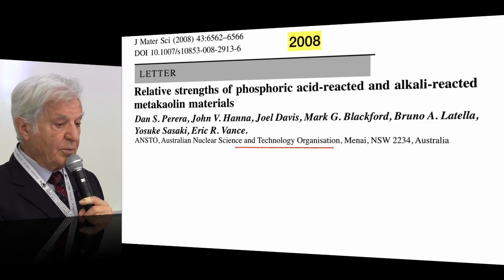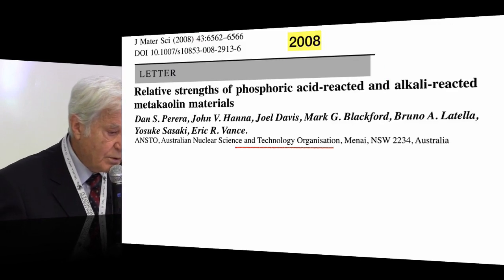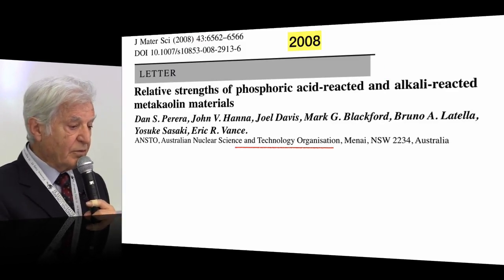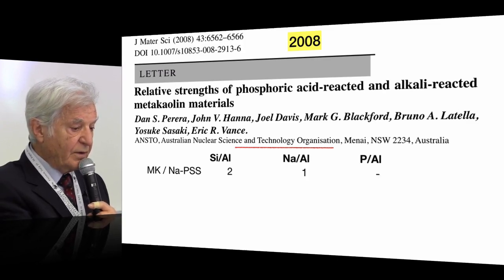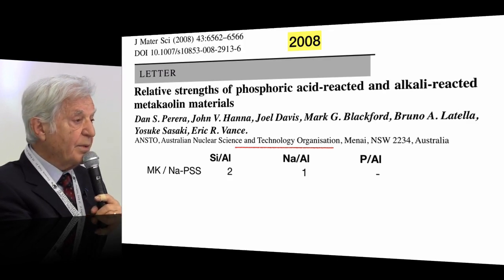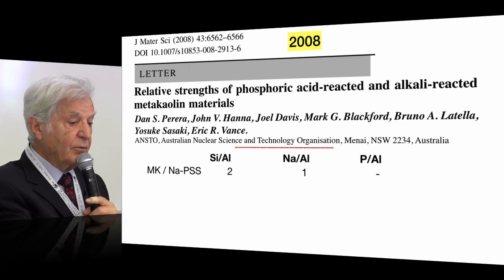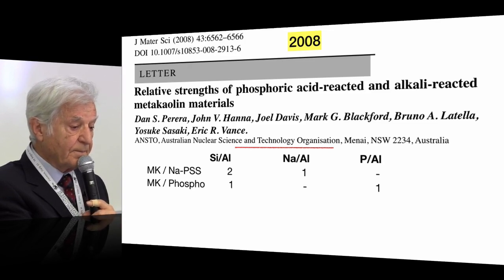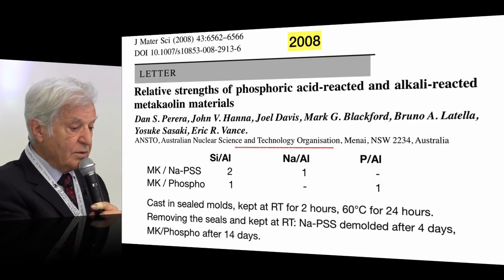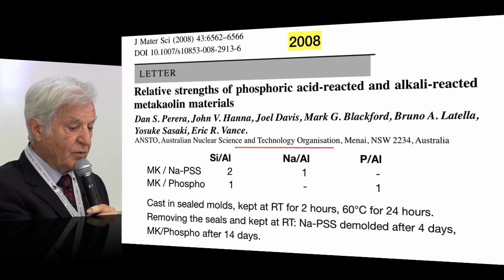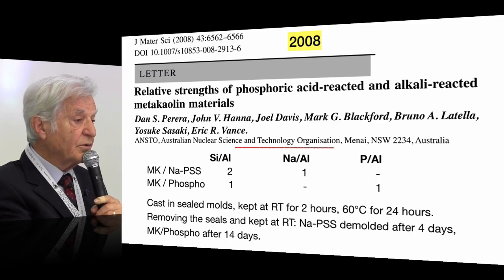So we have a special talk just after this session on phosphate-based geopolymer. The first important paper on that topic, which I consider the first important, was the one published by our friends Perera and his team from ANSTO in Sydney, Australia, where we have Si/Al ratio, Na/Al ratio, phosphate/Al. They compared the metakaolin alkali reaction with the phosphoric acid metakaolin reaction. Metakaolin sodium ratio Na/Al 1, metakaolin phosphate ratio phosphate to Al 1. The material is cast into sealed molds, kept at room temperature for 2 hours, then 60°C for 24 hours. Then the seals are removed and kept at room temperature; the sodium polysialate was demolded after 4 days, the metakaolin phosphate only after 14 days because it is still very wet.